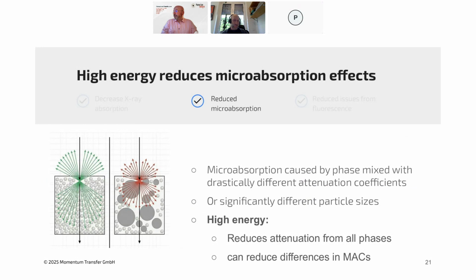For high energies, the whole point is that some particles that are very big or have much larger mass attenuation coefficients will essentially absorb most of the X-rays, and that kind of shadows getting some diffraction from the lighter phases or the smaller particles. And so this can significantly bias your estimations of the relative fractions of those components. So high energy does two good things. One is it reduces the attenuation coefficient for all phases: high energy, less absorption. But the other thing that it does is it can, although not always perfectly, reduce the differences in the mass attenuation coefficients. So that's something to consider.